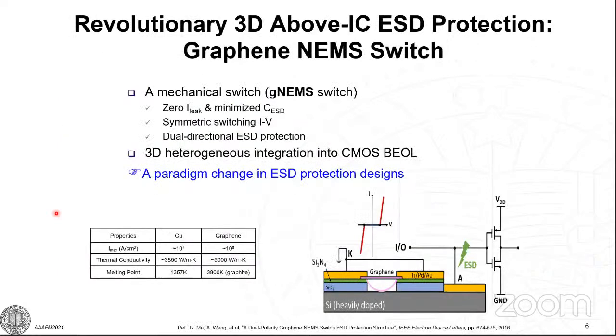Now this comes to the graphene application. From the previous discussion, you can see I have a few required features needed for ESD protection. Electrical conductivity: I want the mobility high so that discharging resistance will be low. Thermal conductivity: I want the generated heat to be dissipated to the outside of the chip efficiently. I want the device really robust, mechanically strong. All those things are good features of graphene materials. Super mobility, super thermal conductivity, high melting temperature, as well as being mechanically very tough, and the strong Young's modulus makes it really, really fast. So it will respond to ultra fast signals. Based on that understanding, we devised two concepts using graphene for on-chip ESD protection IC.